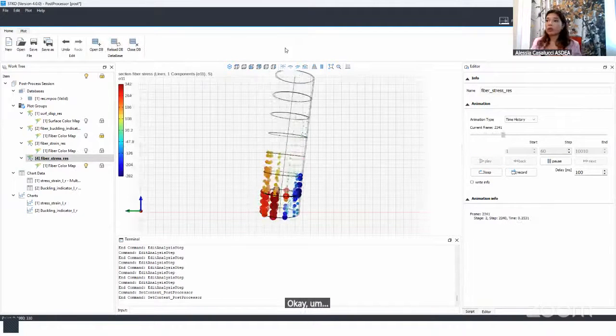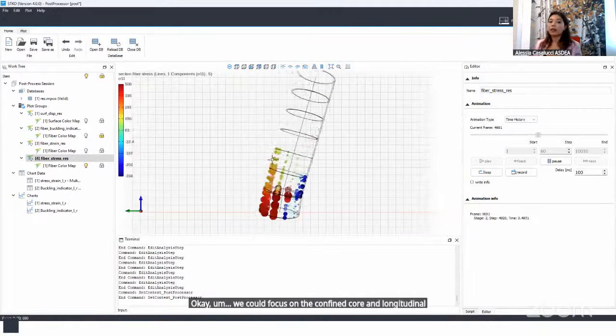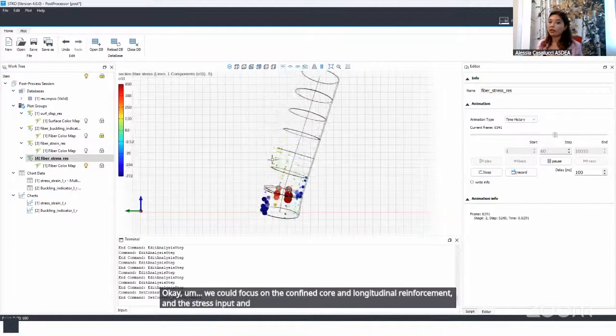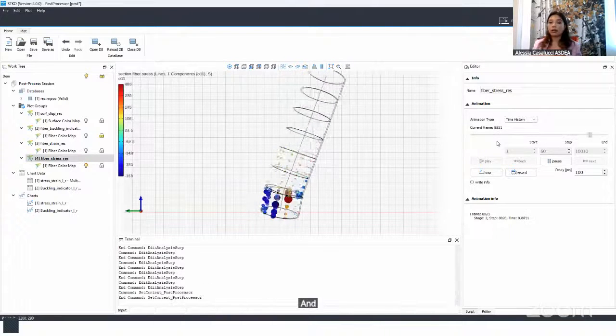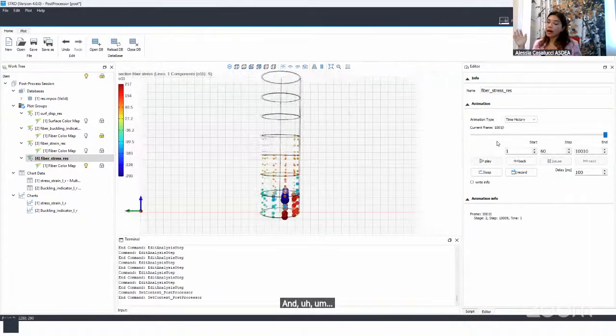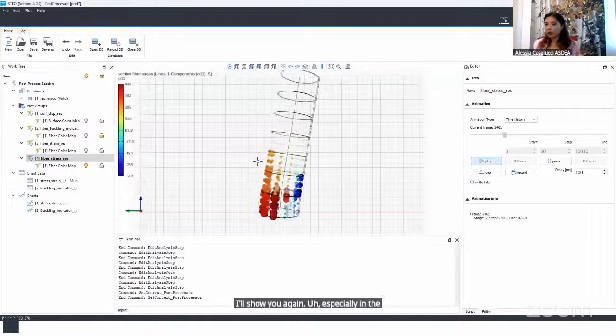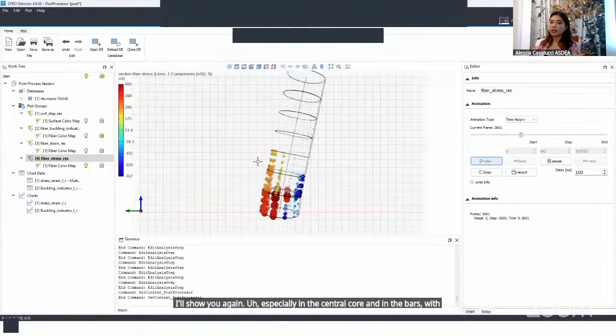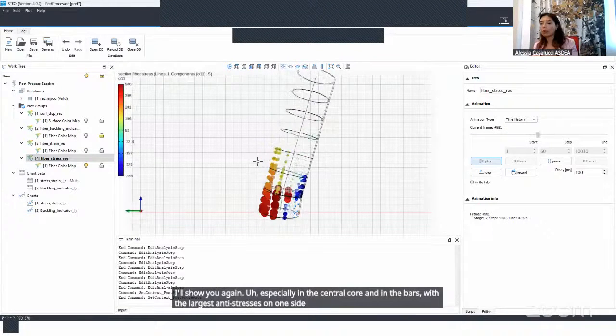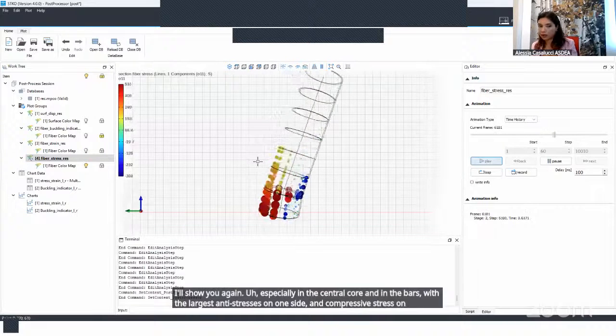Okay, we could focus on the confined core and longitudinal reinforcement. The stress in confined concrete remains stable for the initial cycles, and as the inelastic demand grows, stress redistribution becomes evident. I'll show you again, especially in the central core and in the bars, with large tensile stresses on one side and compressive stress on the opposite side.